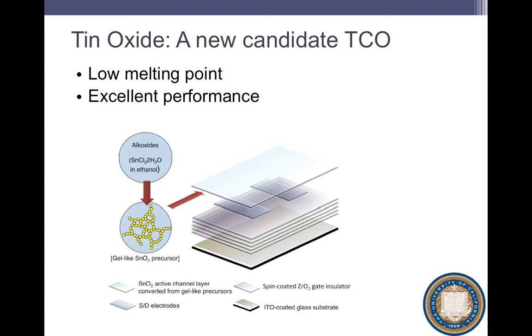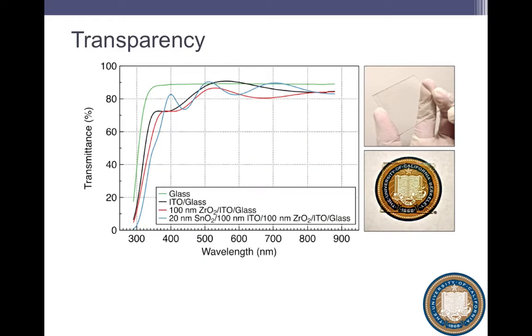Many of you are very familiar with tin oxide. Tin oxide is an interesting material for us for a couple of reasons. It's a semiconductor. It's got a relatively high carrier concentration, so you have to manage that. But it is transparent, has relatively high mobility, and we know how to formulate really good inks out of it. So we formulate these sol gel inks that turn out to be very printable. And then when we print transistors out of them, we get these really transparent transistors.